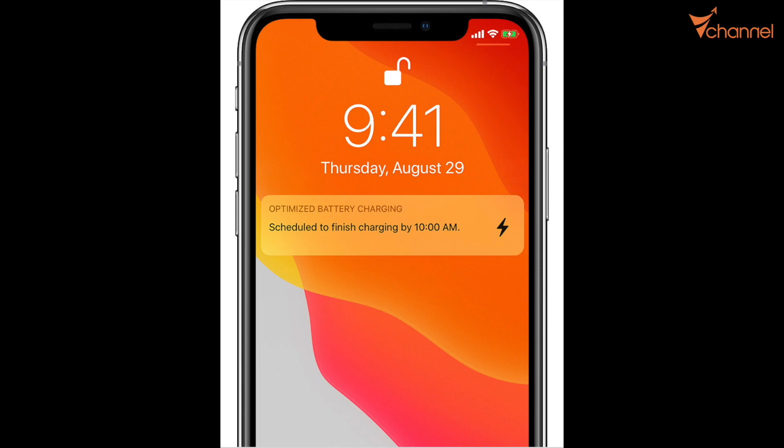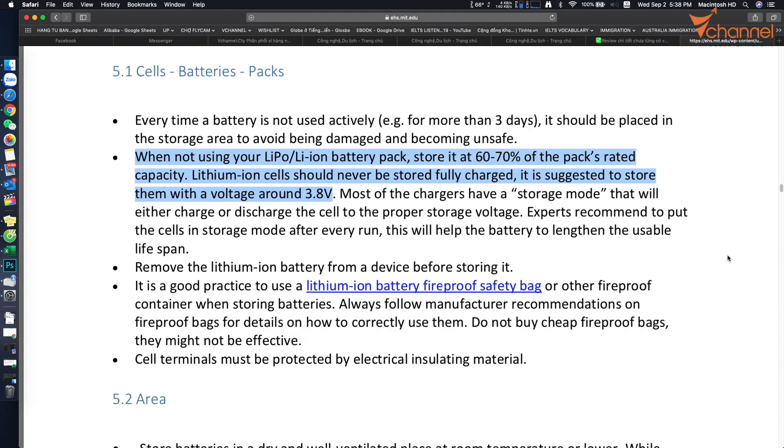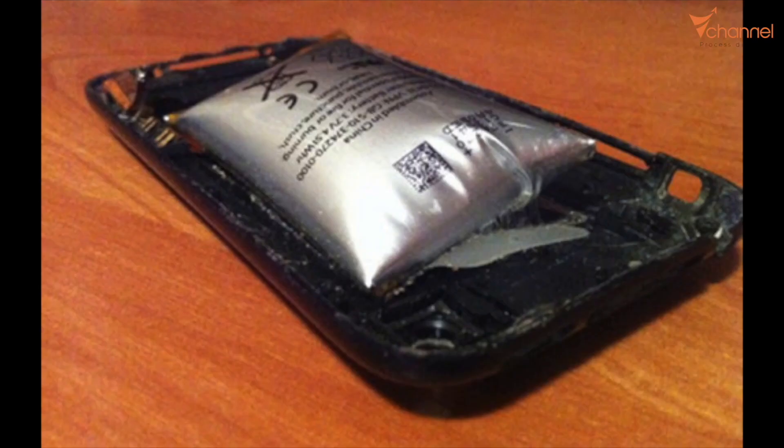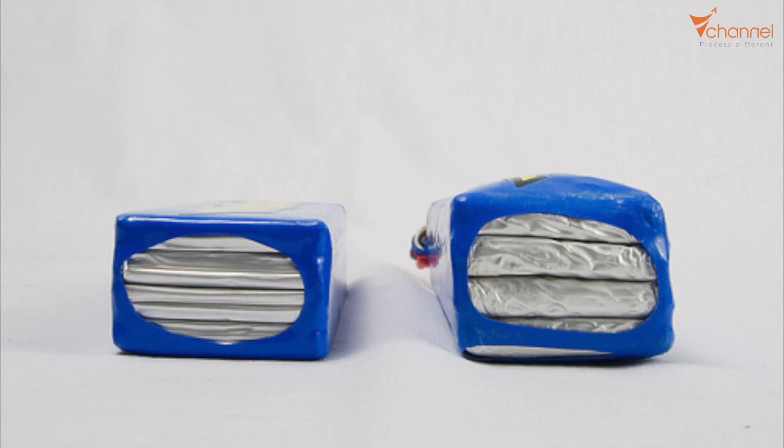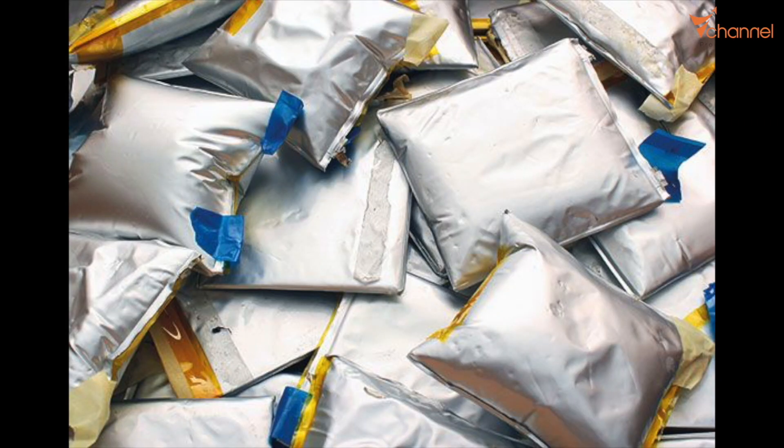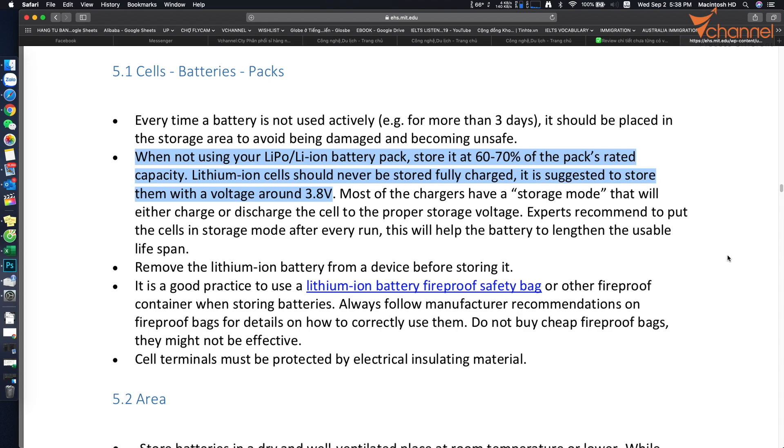One another segment that I want to talk about is what affects battery longevity. That's battery percent. Both lithium-ion and lithium-polymer, if we don't use them, we must bring the battery to storage mode. That is 60 to 70% or 3.8 volts. If we don't use that battery for a long time, but the battery is at very high percent, over 90%, or low percentage lower than 10%, the battery will be damaged, fatten, and decrease longevity seriously. So you usually hear discharge - that is to make the battery reach storage mode, 60 to 70% or 3.8 volts.